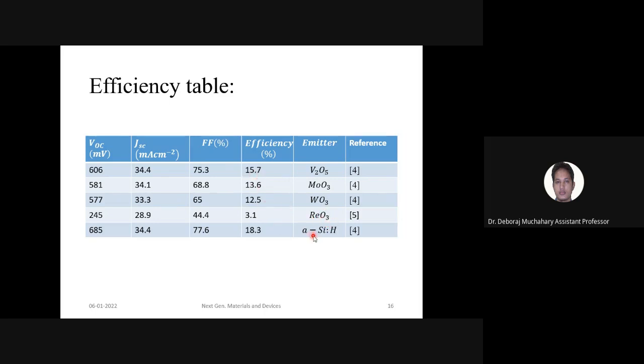Now, what about amorphous silicon? If the emitter layer is not a transition metal oxide but amorphous silicon, that is also incorporated. What is found here is that with amorphous silicon we got around 18.3%, so it is quite high, right? It means you can see there is still a gap. There is the Staebler-Wronski effect problem with amorphous silicon, so if we have to replace it, we will use these materials, but our efficiency is still low as compared to amorphous silicon. So there is still a gap.